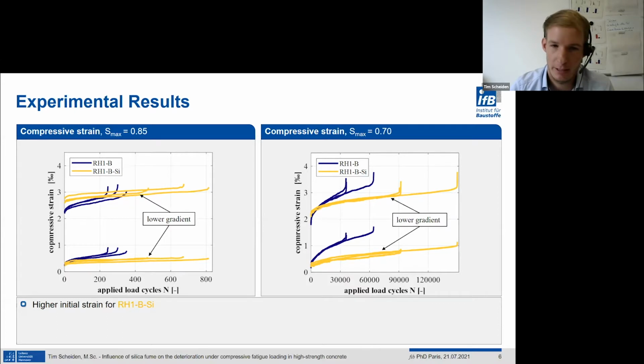The first selected damage indicator I want to present is the compressive strain. On the left side is shown the development of the compressive strain for the higher stress level of 85%, and on the right side, the one for 70%. In general, we see that both concretes on both stress levels have the typical S-shaped curves as we know from other investigations and from the literature.